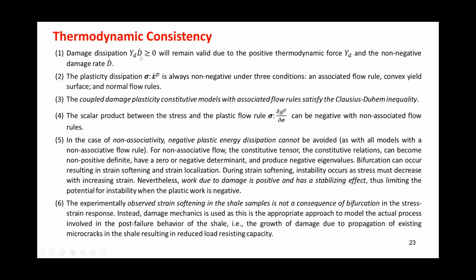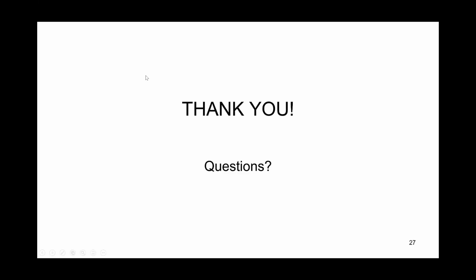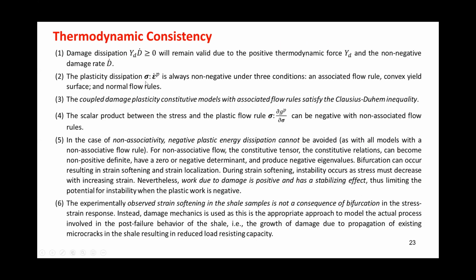We can see that the damage dissipation, which is a function of the damage force times the rate of the damage parameter, is always greater than 0, because the thermodynamic force is positive and the damage rate is non-negative. D is always increasing. The plasticity equation, this one, the product of the trace of the stress tensor and the plastic strain rate, is always non-negative for three conditions. We have an associative flow rule, a convex yield or failure surface, and use of normal flow rules.